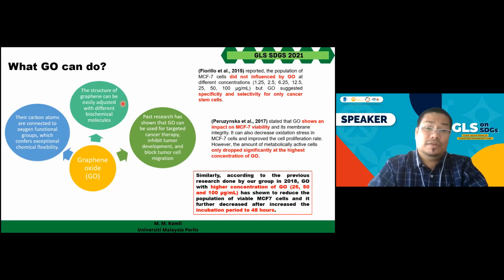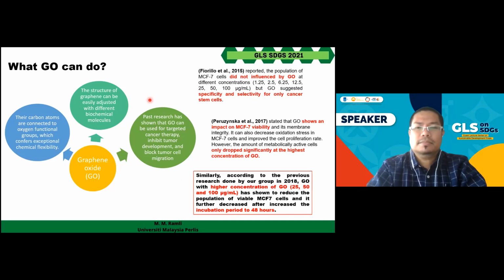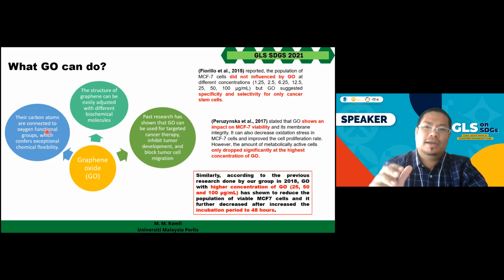So this is what our reduced graphene oxide can do. For your information, we just partially reduce graphene oxide for breast cancer detection. Why? Because of the structure of the graphene, and the functional groups. That's why, as I said before, in some applications we do the full reduction, but in some applications we do the partial reduction. And based on the literature, graphene oxide can target, and at the same time inhibit, the development of breast cancer cells.